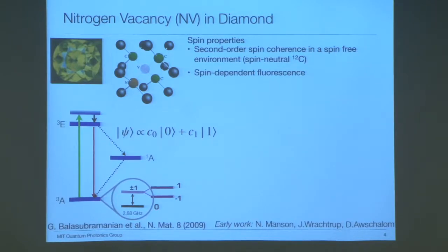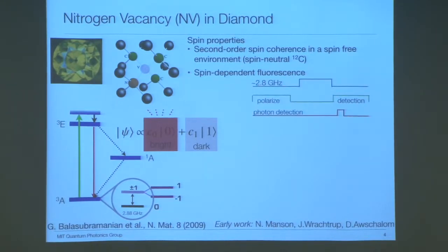And we are able to use 2 of these 3 sublevels to construct a qubit. In our case, we use the ms equal to 0 state as quantum state 0 and ms equal to minus 1 state as quantum state 1. Quantum state 0 is brighter than quantum state 1 because NV has a spin-dependent shelving into the dark metastable state. Here is one example of a spin measurement.